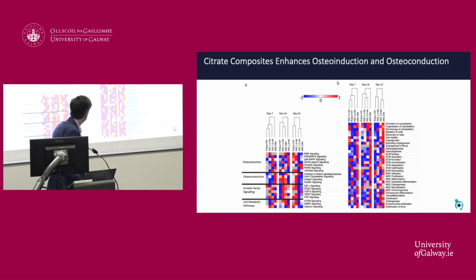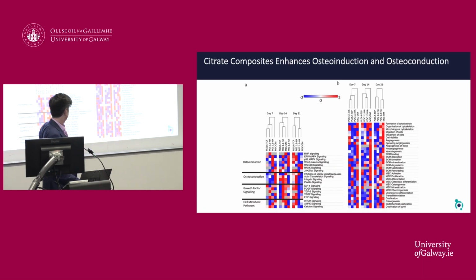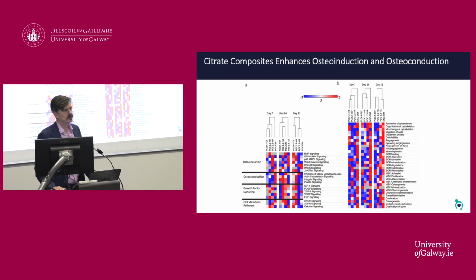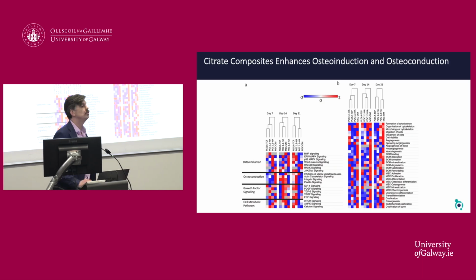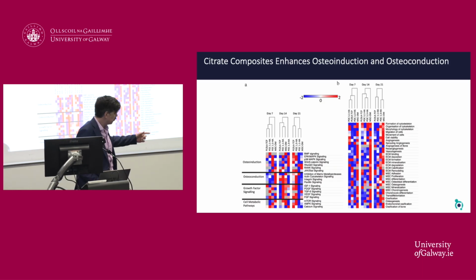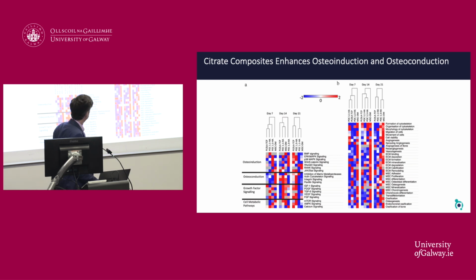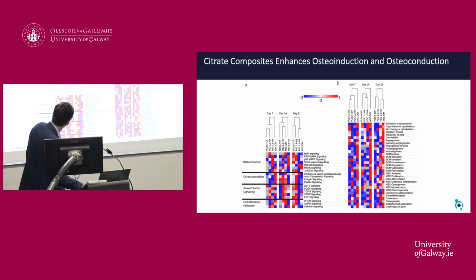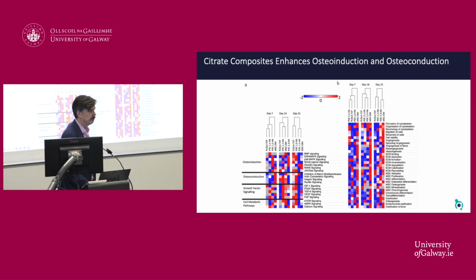We then completed a really extensive in-depth analysis of the transcriptome. So we wanted to look at the transcriptome of these cells at a far greater level, and we performed what's called RNA sequencing. So we looked at hundreds and hundreds of different sequencing events, different transcription events, and we were able to take hundreds of genes and group them into different pathways. So we can look at what happens at the pathway level. When we did this, we were able to quantify changes in things like osteoinduction, osteoconduction, growth factor signaling. These are events really important in bone regeneration. What we found was, if we look at our POC 1.3 material, this is our nicest composite that performed really well.